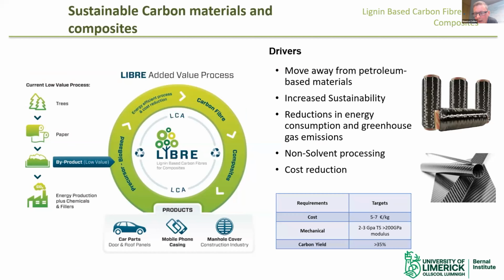So I coordinated a H2020 project called the LIBRE project, and that was about producing carbon fiber for composites from lignin, so a fully bio-based carbon fiber. And the idea behind it was that we're moving from this linear process where trees are used to produce cellulose, and the cellulose is used to make paper, and a byproduct of that paper making process is lignin. And that byproduct is, as I said, 98% waste and 2% is used as a low value energy product. So what we do is we take that waste lignin, and we blend it with other biopolymers using over 50% lignin. So this is the unique part. We use over 50% lignin. We blend it with other biopolymers, and we produce a precursor fiber.